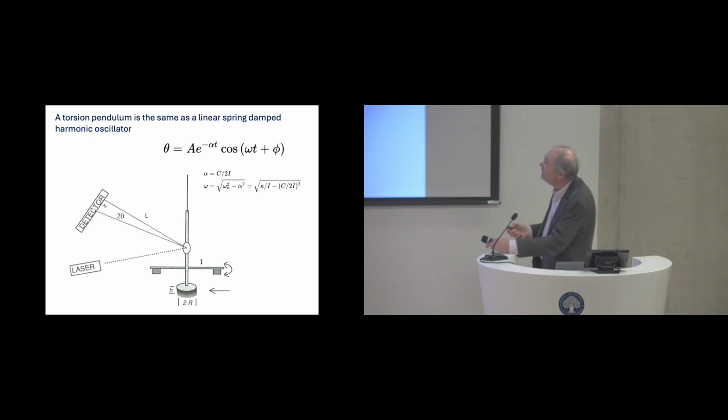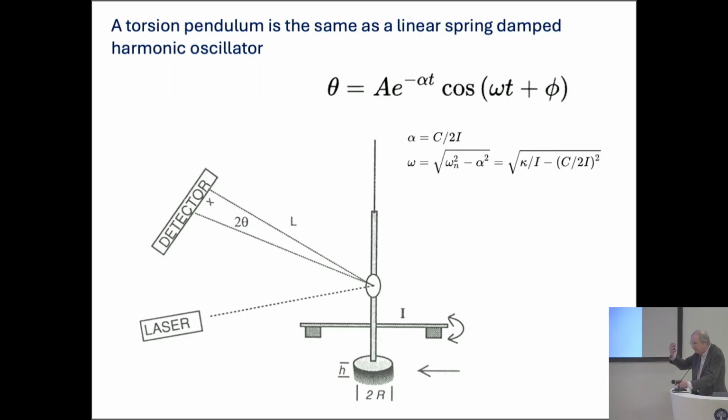And from this we can calculate a frequency. The frequency is the undamped frequency modulated by some kind of damping term. It's a tiny term, so you can sort of forget it. And the decay of the amplitudes will give us this kind of friction constant, which will give us a so-called loss modulus.